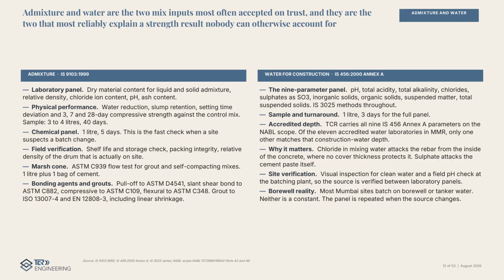Admixture and water are the 2 mix inputs most often accepted on trust. And they are the 2 that most reliably explain a strength result nobody can otherwise account for. On the admixture side, 1 liter and 5 days gives you the chemical panel under IS 9103. Dry material content, relative density, chloride ion content, pH and ash. On the water side, 1 liter and 3 days gives you the full 9 parameter panel that IS 456 Annex A actually requires. TCR carries all 9 on the accredited scope. Chloride in mixing water attacks the rebar from inside the concrete, where no cover thickness protects it.